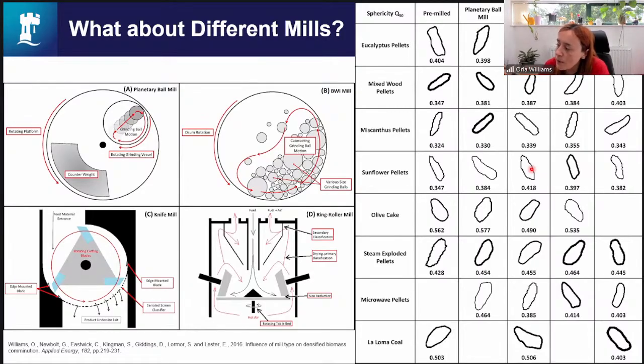And we can see that the actual fracture mechanism is abrasion and attrition, because pellets are made by shredding the material to start with. They're pelletized, and then the aim of your milling process is just to break them back down to the original particles.